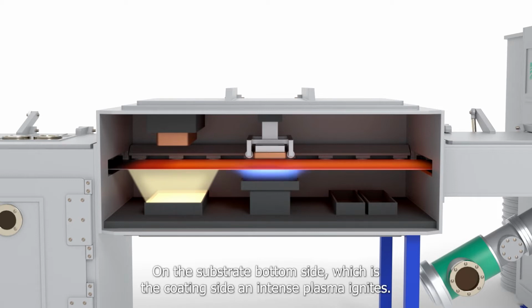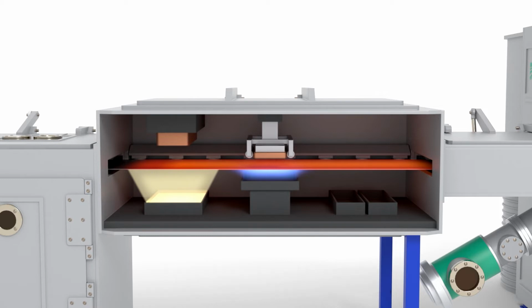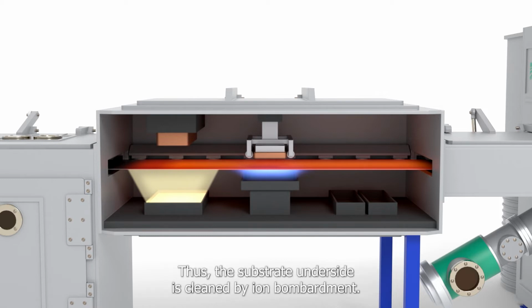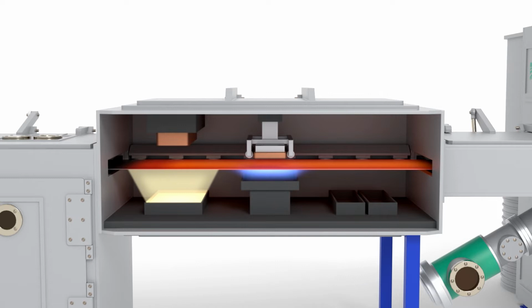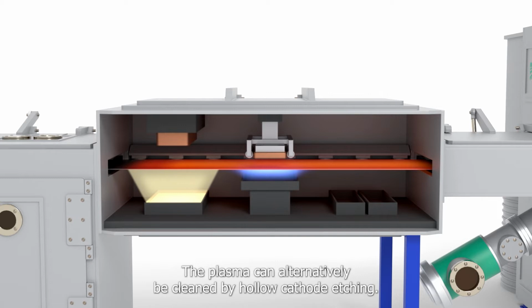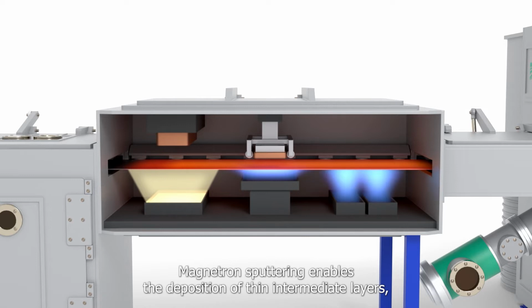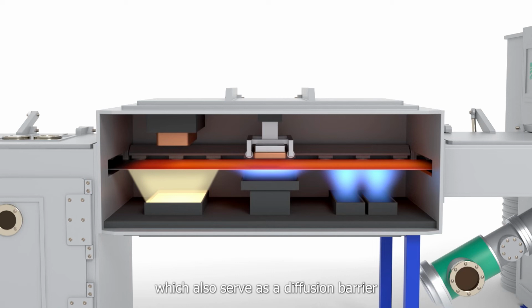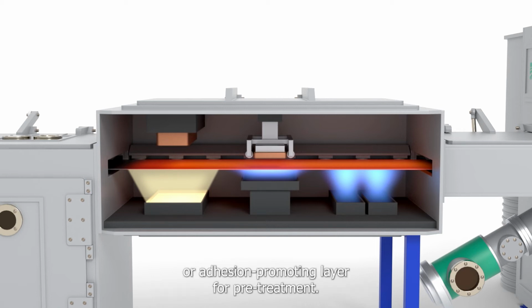On the substrate bottom side, which is the coating side, an intense plasma ignites. Thus, the substrate underside is cleaned by ion bombardment. The plasma can alternatively be generated by hollow cathode etching. Magnetron sputtering enables the deposition of thin intermediate layers, which also serve as a diffusion barrier or adhesion-promoting layer for pretreatment.